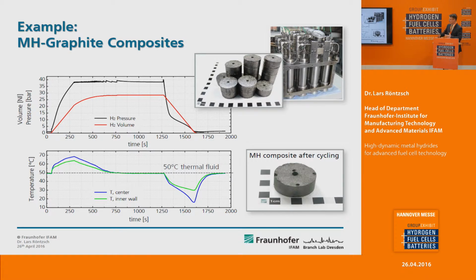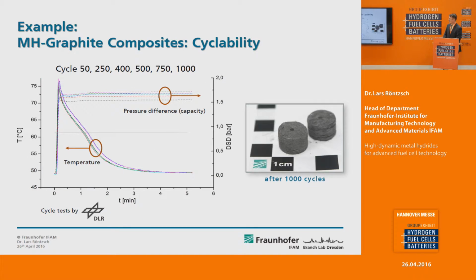So one can really get into the time frame of high pressure vessels, where 3 to 5 minutes are state of the art. This is also possible with solid state storage materials like hydrides. We have much lower operation pressure and even higher volumetric storage density. You can even increase the dynamics to very few seconds. In this case, about 90 seconds are enough to fully hydrogenate such a metal hydride composite, and you can do it over many, many cycles.